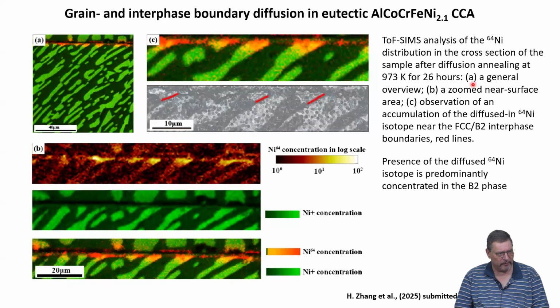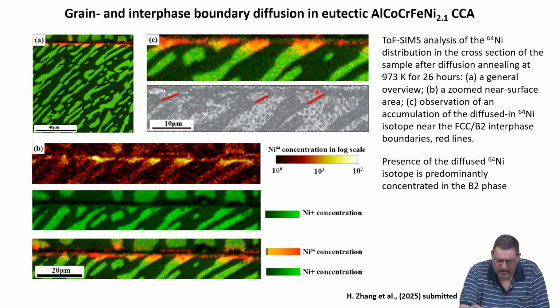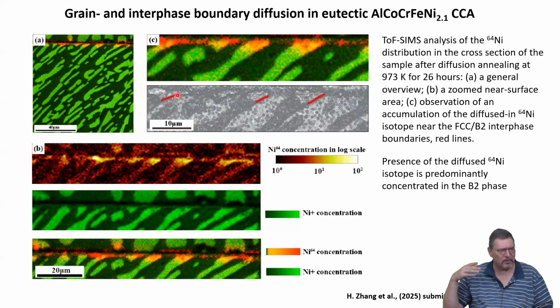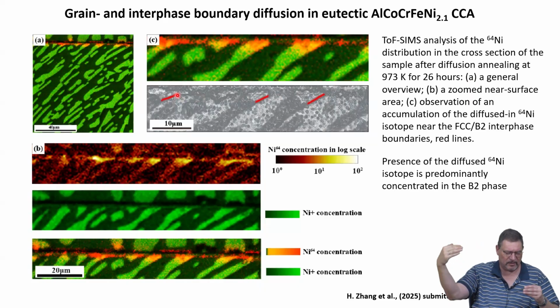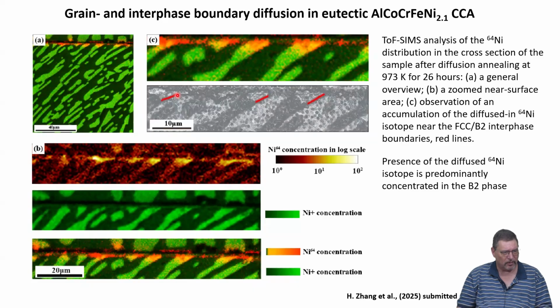We also did time of flight secondary ion mass spectroscopy measurements in order to confirm, because for such a complex microstructure it might really be good to have visual information about where your tracer goes. In this case, again, it's non-radioactive but a stable isotope. And basically you see some of the stable isotopes enriched in these regions where the tracer runs along a phase boundary and comes and touches or runs against an interface boundary. So this is really some verification that we have interpreted the radio tracer diffusion correctly, because there we cannot have any visual information about how and where the tracer really was going.